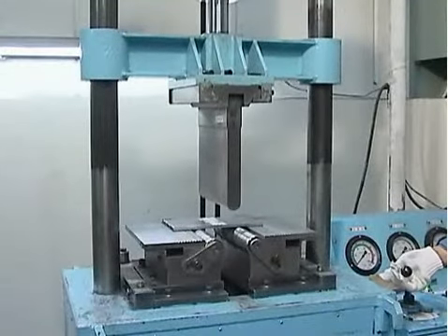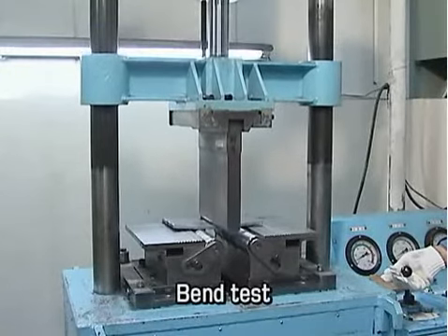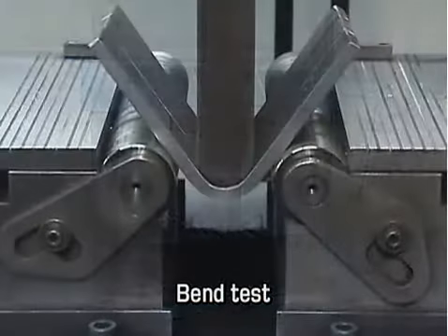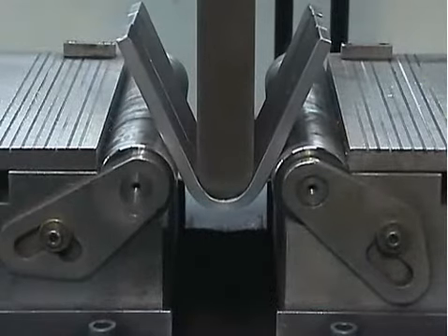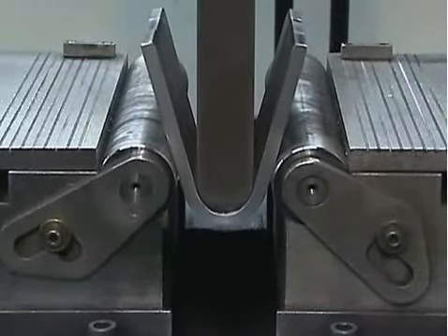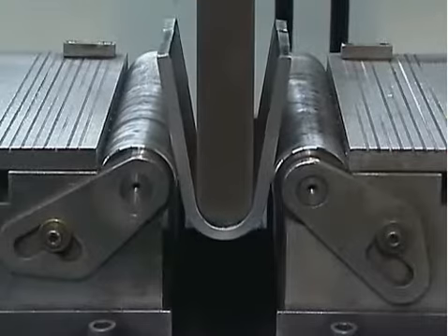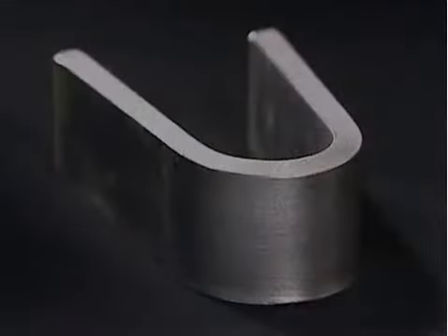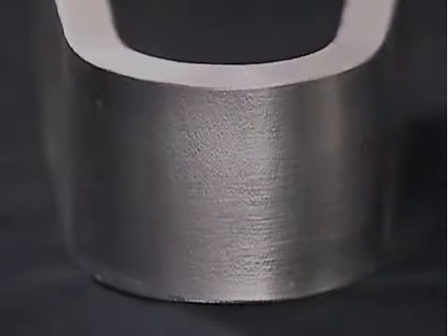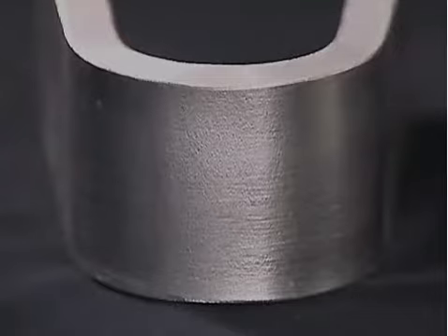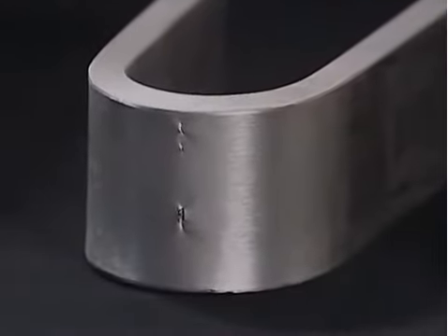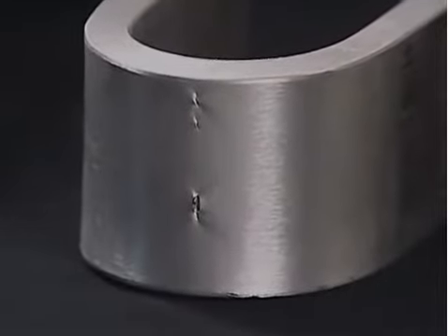The bead has a uniform width and is formed continuously. Next, a bend test checks the mechanical properties of the test piece. The test bar is bent 180 degrees into a U shape to check the soundness of the weld. Let's see the result. It's a sound weld. These are examples of defects, cracking and breakage.